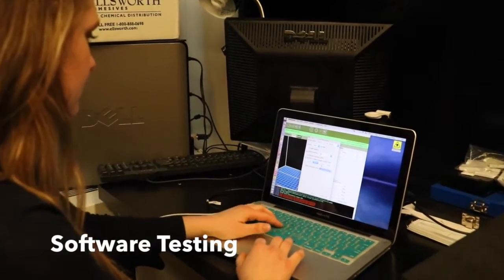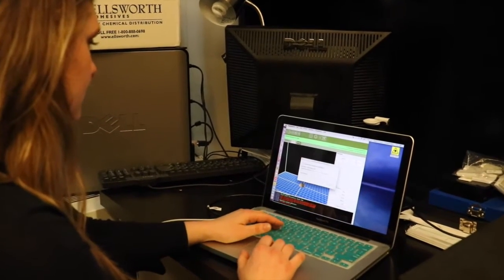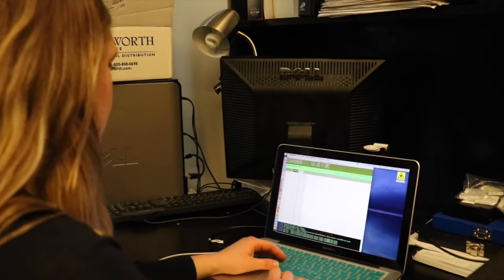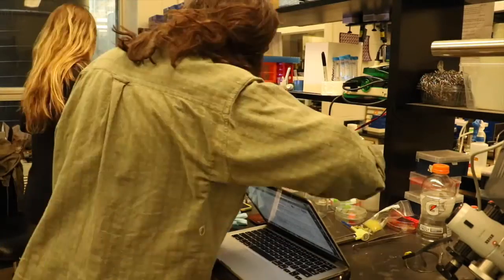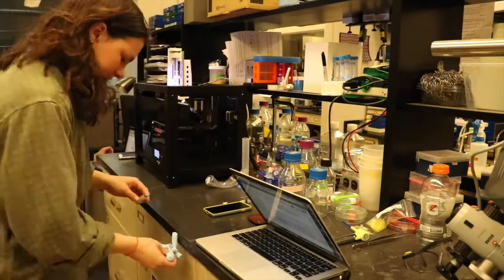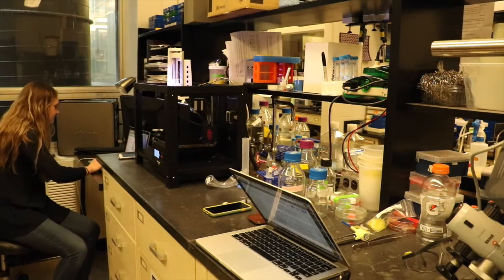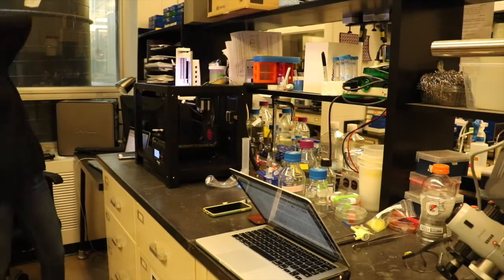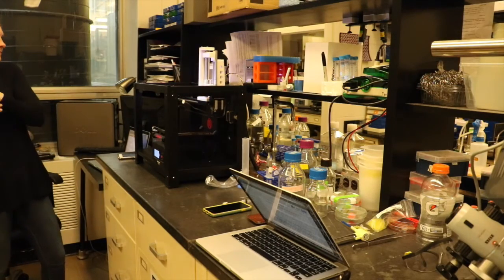Testing proceeded with the printer and a cheaper material, alginate. Here we used the Replicator G to generate a G-code used to control the MakerBot. The parameters we changed were filament diameter, nozzle diameter, feed rate, and added a movement of the nozzle between layers to allow for curing. After about a week of these tests, we had determined a good set of parameters that dispensed the right amount of material from the syringe.